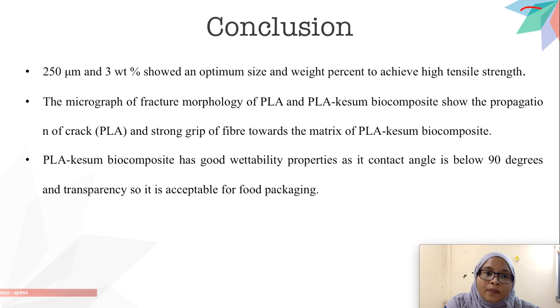Okay, to conclude, 250 micron and 3% showed the optimal size and weight percent in order to achieve high tensile strength. Next, the micrograph of the fracture morphology of PLA and PLA Kesum biocomposite shows the propagation of cracks for PLA and a strong grip of the fiber towards the matrix of the PLA Kesum biocomposite. And the last one is that the PLA Kesum biocomposite has good wettability properties as its contact angle is below 90 degrees, and it also has good transparency, so it is acceptable for food packaging, if we want to make it food packaging.